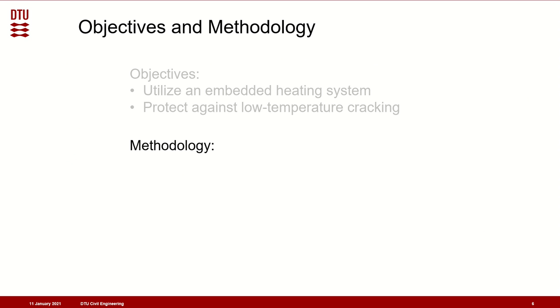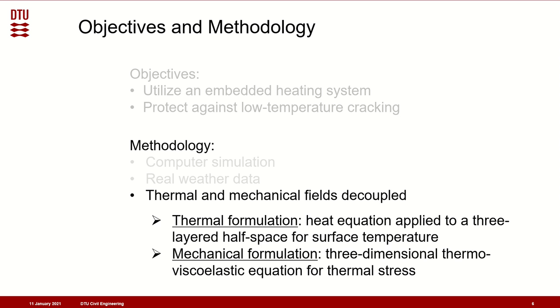To this end, computer-based calculations were carried out, in which real weather data was utilized. The thermal and mechanical fields were decoupled. The thermal formulation considered the heat equation applied to a three-layered half space to acquire the surface temperature, while the mechanical formulation considered a three-dimensional thermoviscoelastic equation to acquire thermal stresses at the surface.